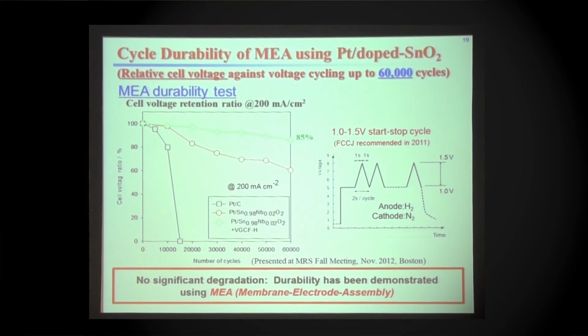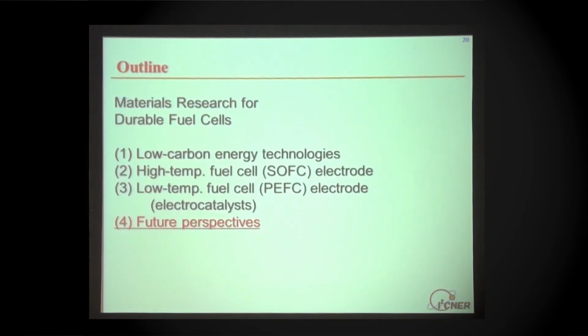But now we are very happy to announce that we presented these new results last week. Now we can also show much more stability, and even after 60,000 cycles, corresponding to the lifetime of fuel cell vehicles, we can retain 85% of the initial cell voltage. This is a great improvement, and we also show electrochemical performance comparable to the state-of-the-art platinum carbon electrocatalyst. Therefore, we have shown that this material is stable from the materials viewpoint, and also stable in the MEA, that is, the fuel cell, showing not only durability but also comparable performance.